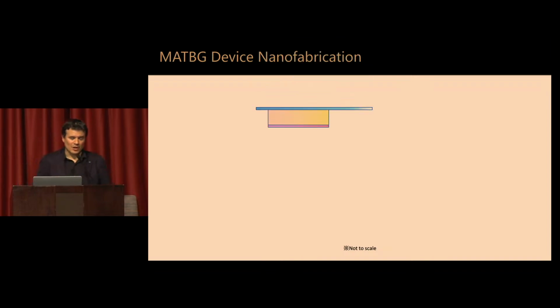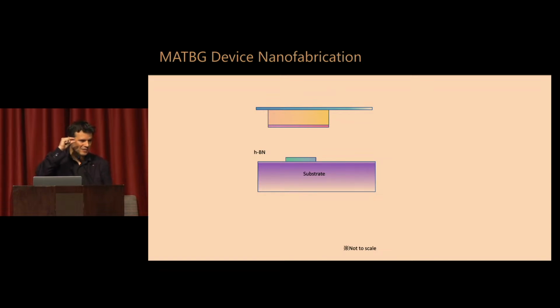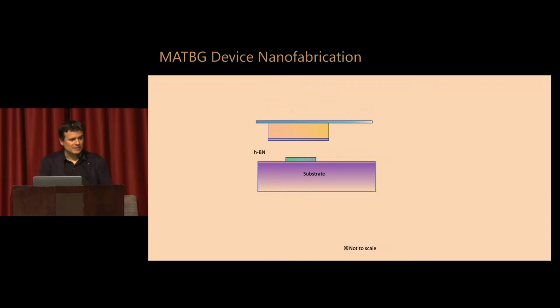It's very simple, not quite as simple as Scotch tape and crystals of graphite, but it's actually quite simple, much simpler than you may think. So we start with a glass slide, which has a sticky polymer attached to it. And then we bring a substrate which has a thick layer of hexagonal boron nitride, 10 nanometers. I mean, still thin, but not atomically thin. This is going to be just an ultra-flat substrate, very comfortable for the graphene to be attached to. So I come with my sticky polymer, and I pick up this hBN crystal.